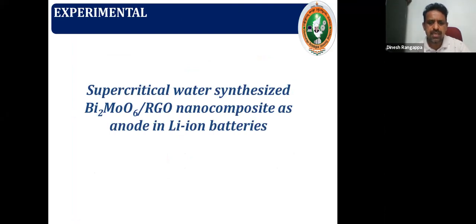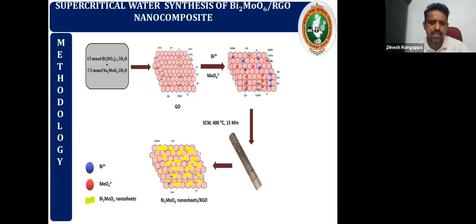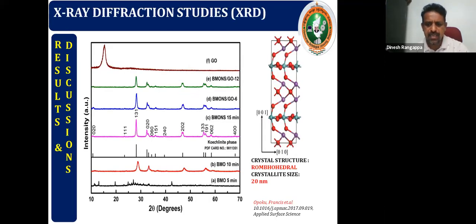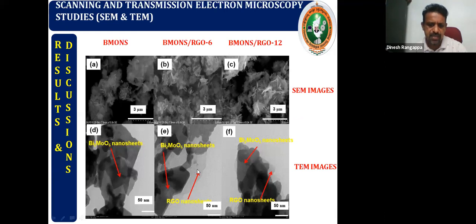So next, we prepared bismuth molybdate RGO composite using supercritical fluid conditions. Similar to the conditions I explained for lithium iron phosphate and silicate, we studied the crystal structure, and a similar crystal structure with an even smaller crystallite size compared to hydrothermal was obtained, about 20 nanometer crystallite size. And here you can see the hierarchical heterostructure arrangement. Bismuth molybdate sheets are coated on the graphene sheet, the RGO sheet.